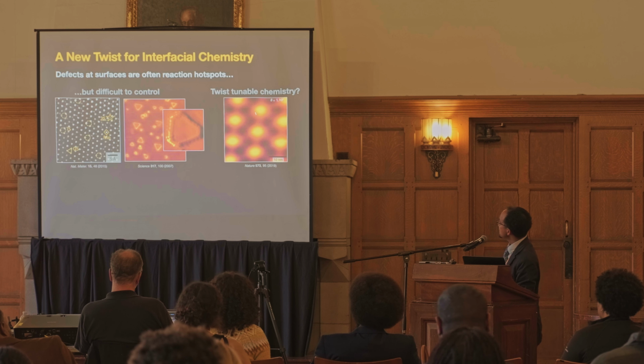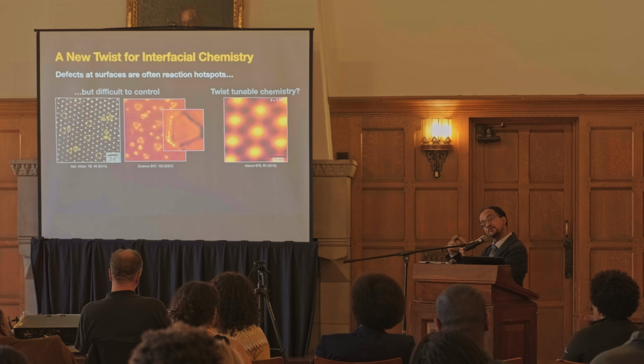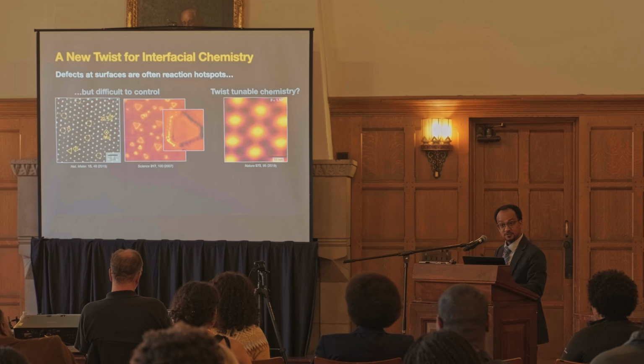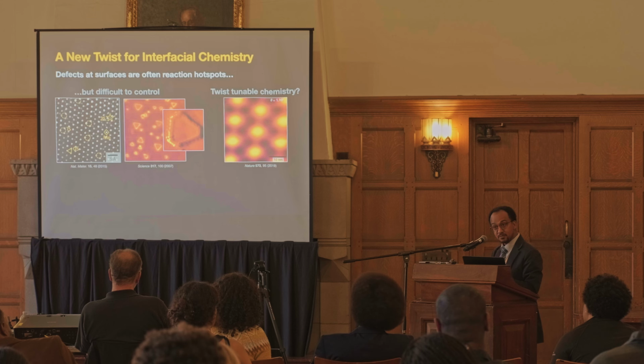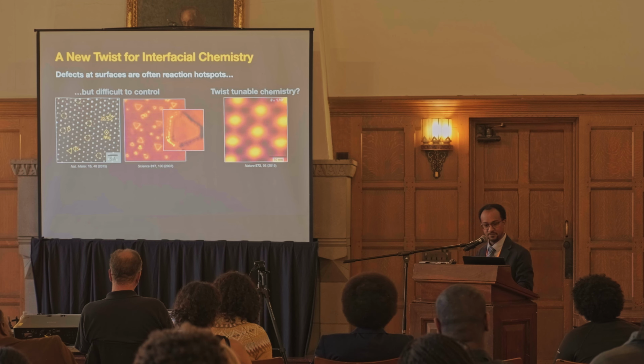But defects are really difficult to control. It's easy to draw a perfect structure. It's very difficult to get a perfect structure. But what is maybe more difficult than that is to say, okay, I'm going to have an imperfect structure exactly the way I want it. And so what we discovered is that by twisting these layers, the same kind of effect that at very low temperatures leads to superconductivity can be used to create effectively tunable defects, so that where the electrons like to sit in these twisted structures can be controlled by twist, whereas they usually are controlled, or ill-controlled, by defects on regular surfaces.